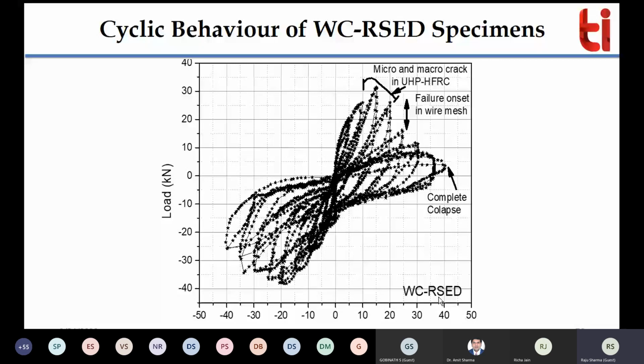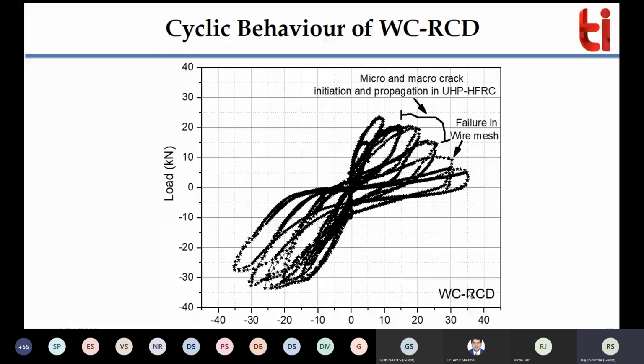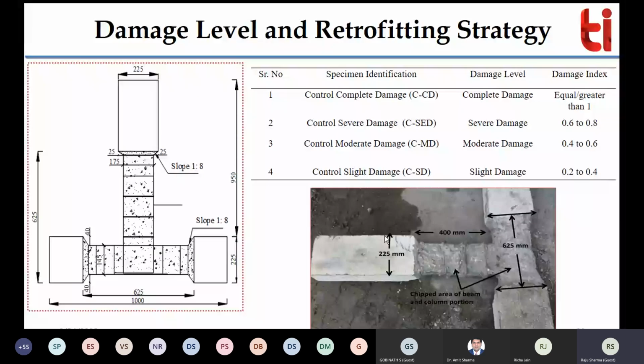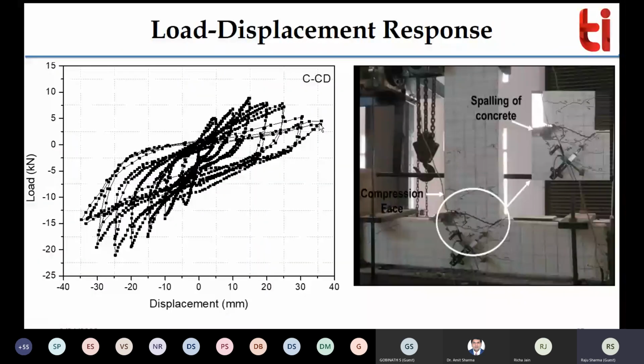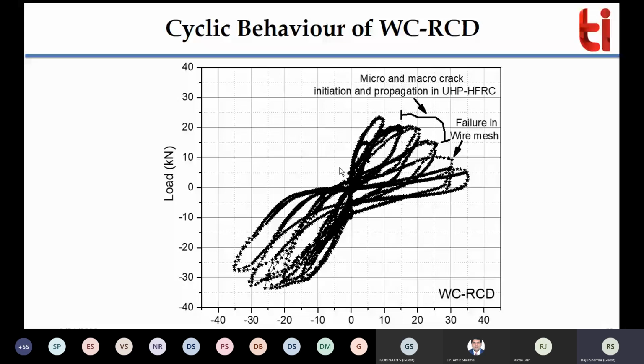It is showing the complete damage. So this was the complete damaged specimen, and then retrofitted by UHP HFRC overlay, we achieved 25 and nearby 35. So complete damage after retrofitting again gained the strength of the original specimen, because in the original specimen, if you see here, you can see the 35 displacement over here, and here we only had 10 kilonewton capacity. But if you see over here, you can see 35 again after complete damage and then retrofitting, you are again able to get the strength of the original specimen, right?